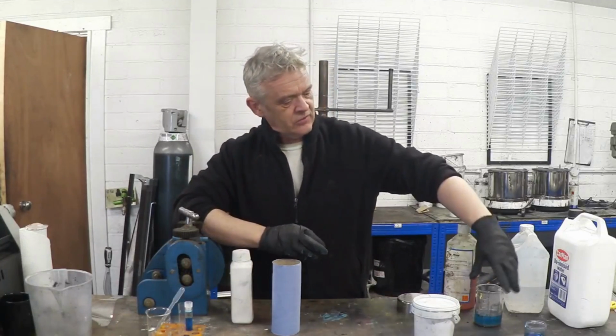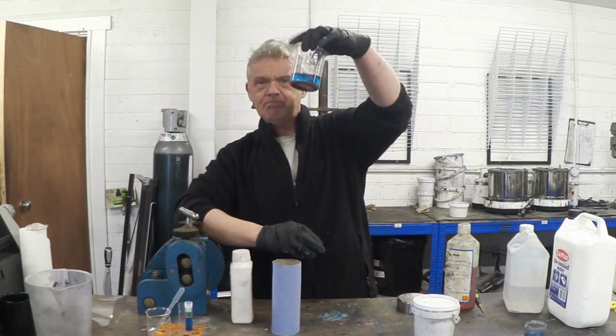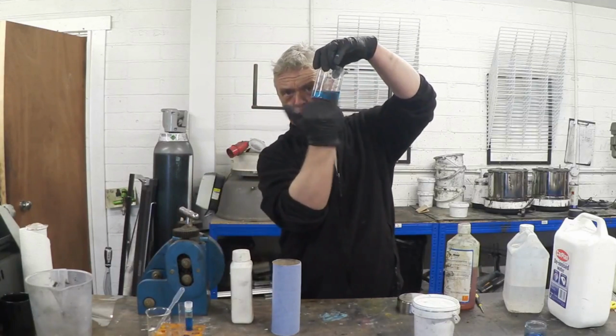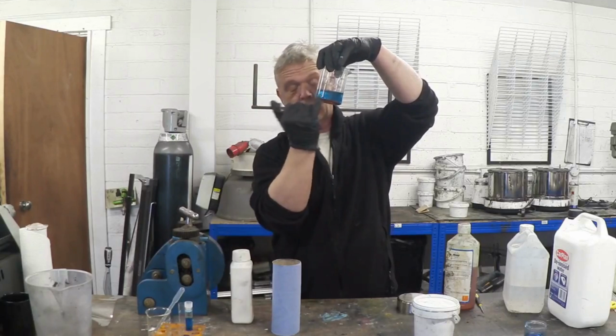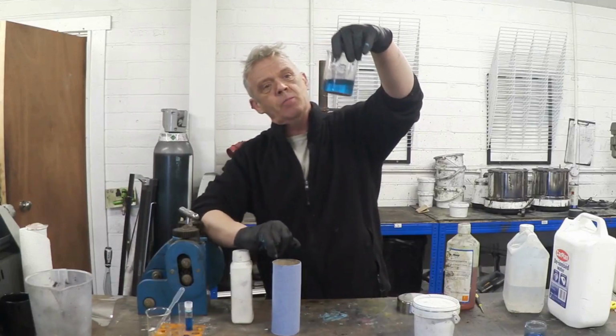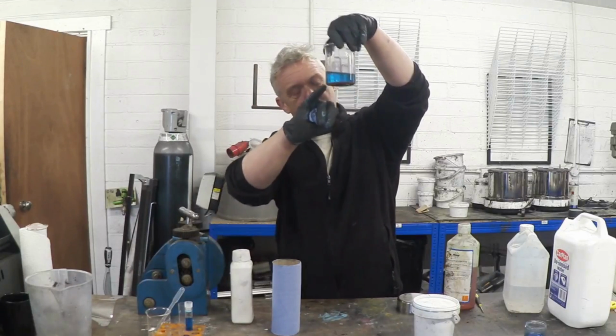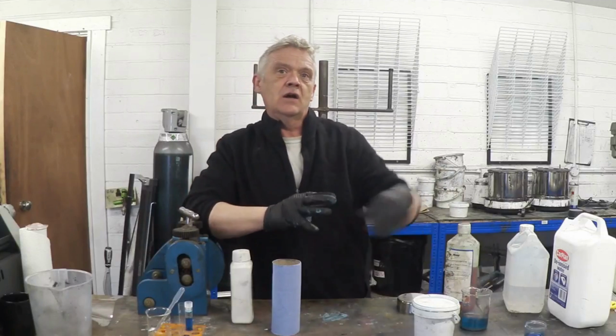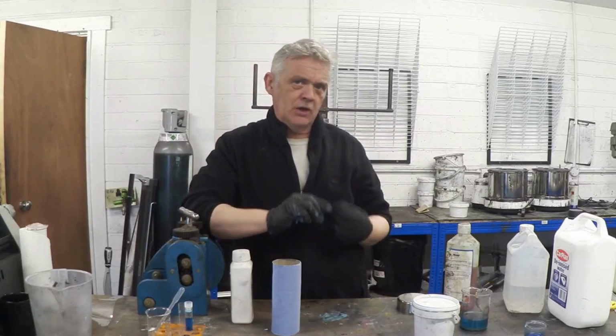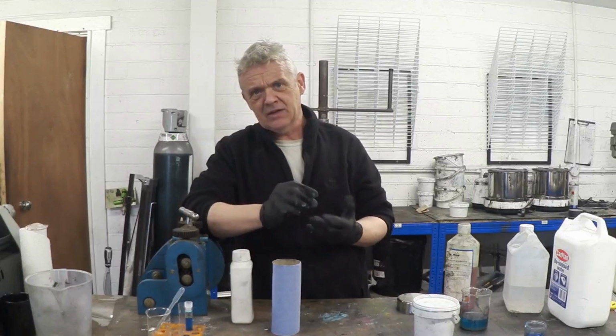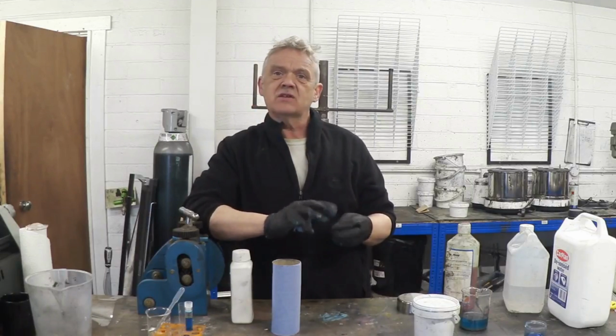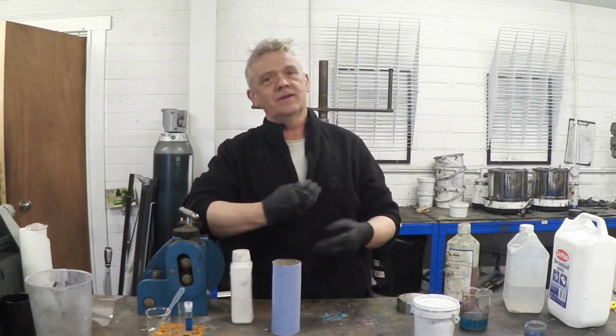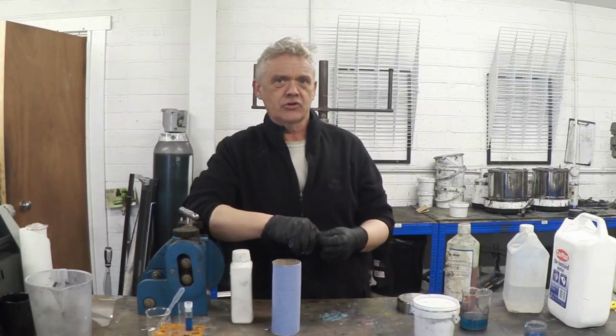Now, the first thing that it can do is, if you add a bit of water, you'll form this blue formate solution. That's obviously a copper two salt. And at the bottom, you'll see a salmon pink layer. That salmon pink layer are copper particles. They're not nanoparticles. Copper nanoparticles are black. This salmon pink tells you that it's quite small, but still in nano terms, relatively large copper particles.